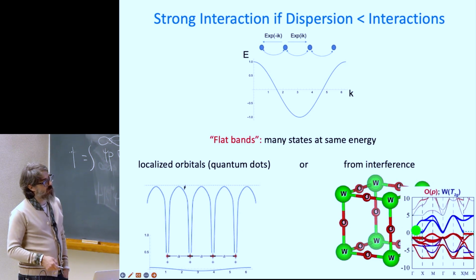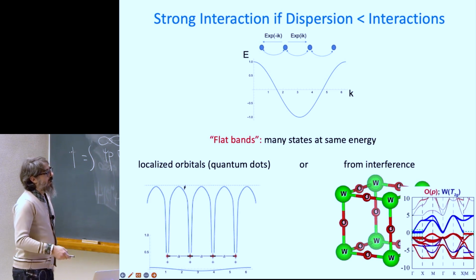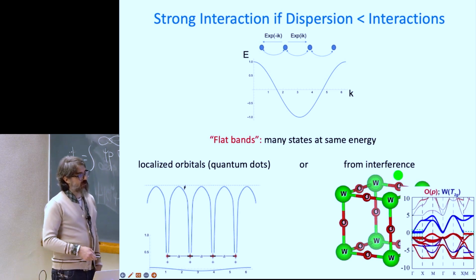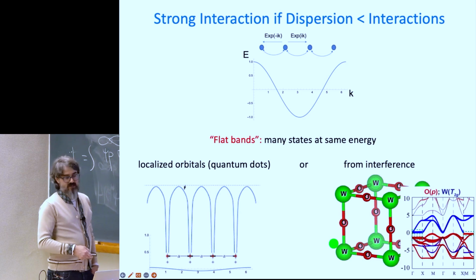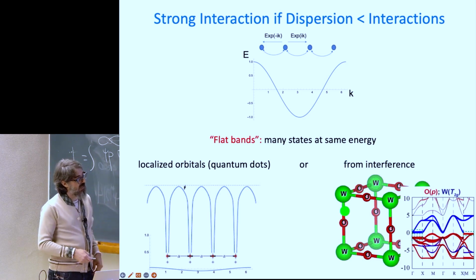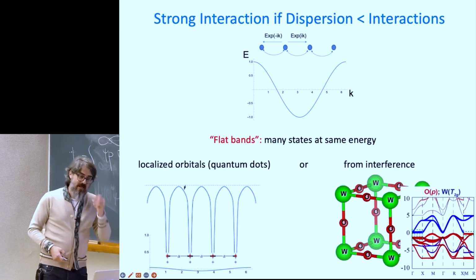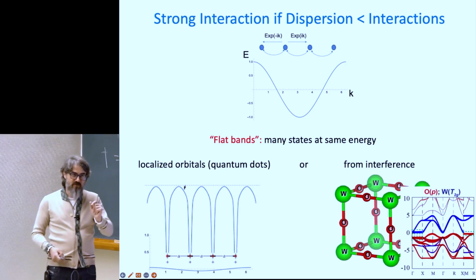Okay, and the way you know this is that these are some momentum axis in the Brillouin zone. And it's got a flat band, and now you start with a dispersive band. And this dispersion is huge. It's 3 electron volts, right? It's pretty large. And the reason for these flat bands is really this material looks like a special lattice. It's called the Lieb lattice, a bipartite lattice with 3 oxygen and a tungsten, okay? And these lattices have flat bands because of quantum interference, basically.